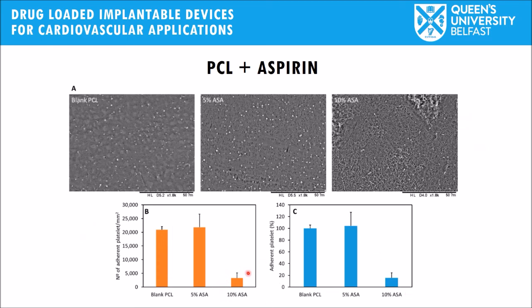Vascular grafts containing 10% of aspirin presented lower adherence of platelets to the surface whenever the materials were incubated with blood, and the platelets on the material were counted. So we discovered that vascular grafts prepared containing 10% of aspirin were resistant to the attachment of platelets, which would subsequently lead to the buildup of blood clots.